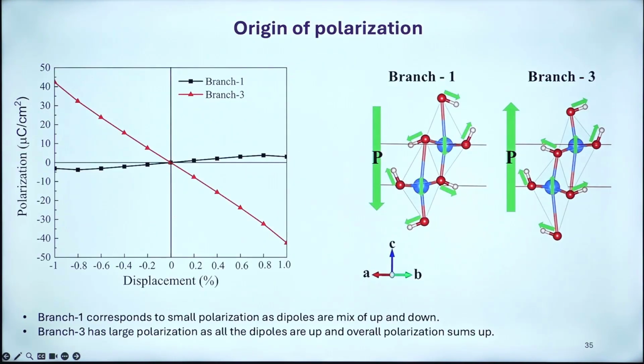So now we try to compute the polarization again as a function of displacement, because as I told you, this is a displacive transformation. This is simple. By moving the atoms, we calculate the energies and see how they compare with the original energy, and then take the difference. For each displacement we do this for positive and negative displacement, and then we could see this for branch 1 and branch 3 here.